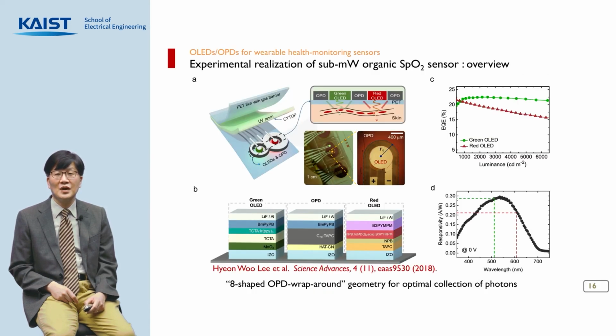So in the proposed scheme, a photodiode looking like the alphanumeric character 8 wraps around the green and red OLEDs as shown here. So please note that the circle around the green light is smaller in diameter than that surrounding the red OLED. This is the actual photograph of the sample we fabricated with the device structure shown below. We used state-of-the-art phosphorescent OLEDs for red and green light sources and C70 TAPC bulk heterojunction organic photodiodes, which have a decent responsivity in the visible spectral region.